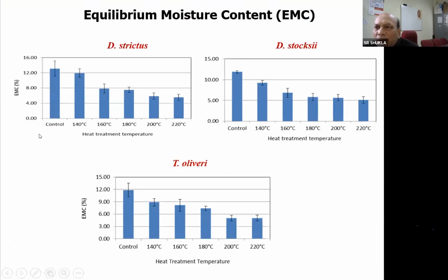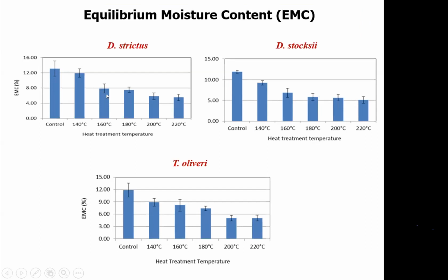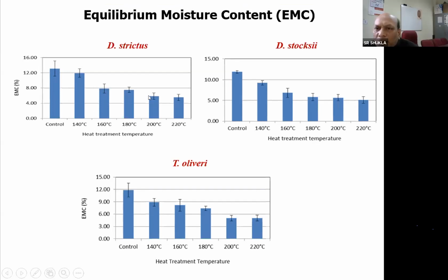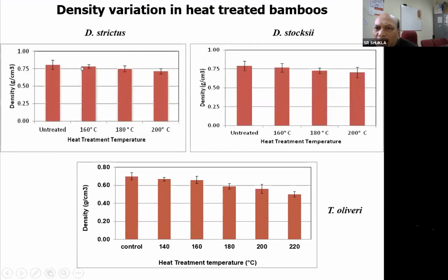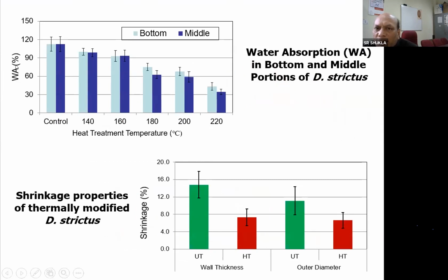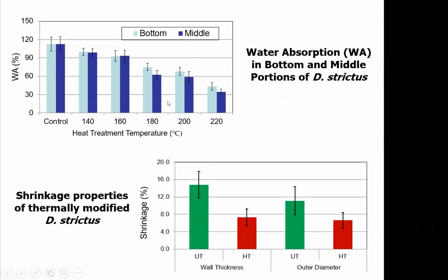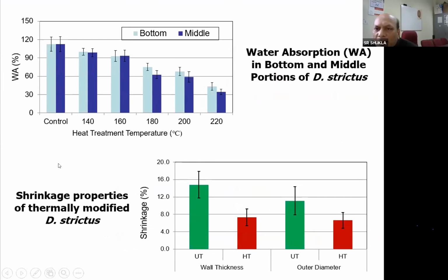These are some of the graphs which will show the variation in the properties. The equilibrium moisture content of the control bamboo is around 12 to 14%, but it will come down to 5 to 7% when bamboo is treated to different temperatures. This is the density, not much variation in the density when bamboo is treated to high temperature. This is the water absorption percentage. You can see that bamboo becomes water repellent once it is treated at high temperature.